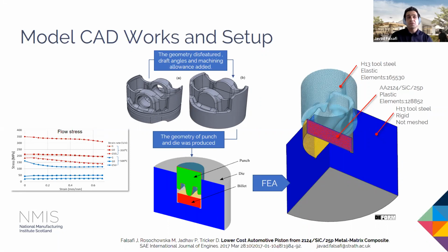Very important part of this was the material. The material was aluminum 2124 with 25% silicon carbide. And it was manufactured through powder metallurgy. This composite was modeled as rigid plastic, isotropic material, and we characterized the flow curves with compression tests at various temperatures, strains and strain rates. You can see some of the flow curves on the left-hand side, 2 temperatures at various strain rates.